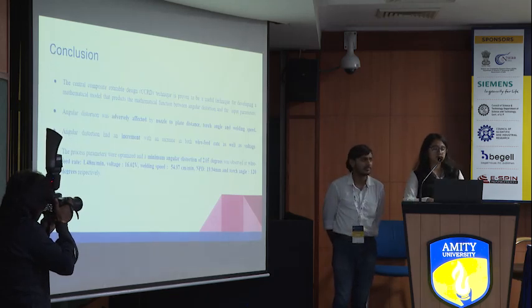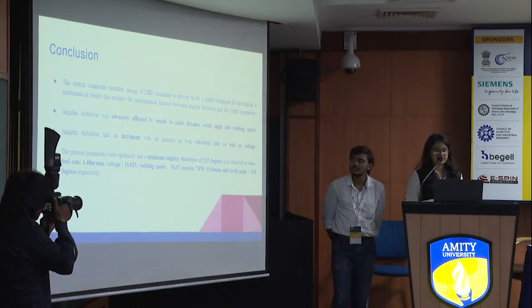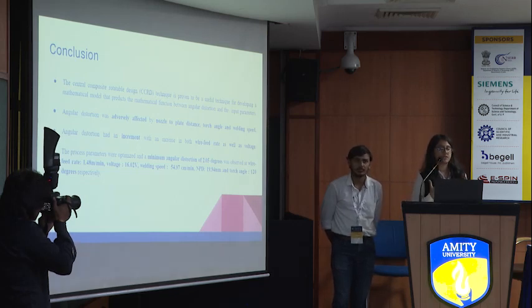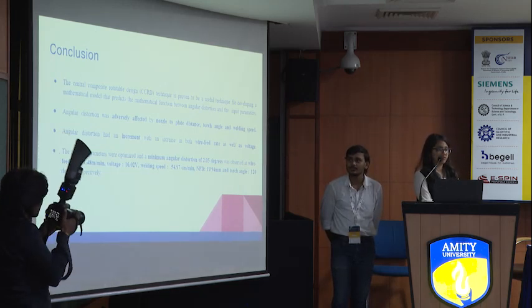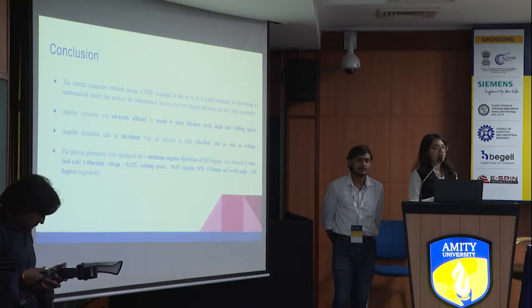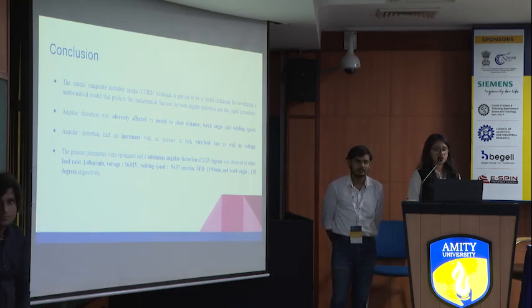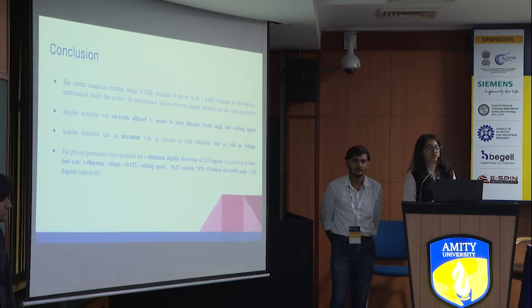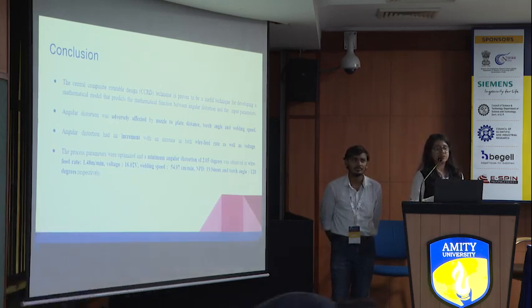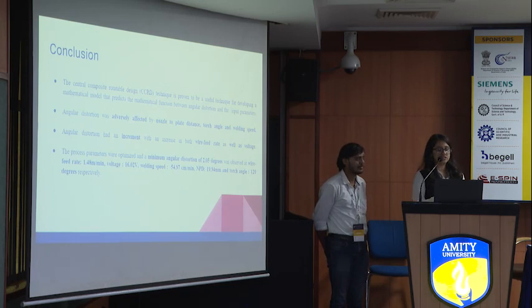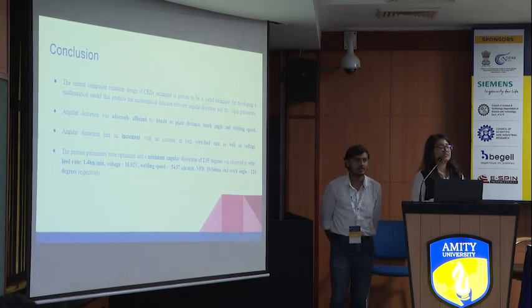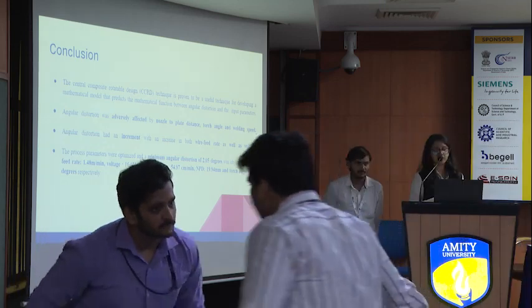The conclusion was pretty simple: the CCRD technique, central composite rotatable design, proved to be very helpful while we were developing the mathematical model to predict the angular distortions for our given input variables. Input variables were welding speed, voltage, nozzle to plate distance, torch angle, and wire feed rate. When we increase torch angle, welding speed, and nozzle to plate distance, the angular distortion has an inverse relation. On the other hand, there was an increment in angular distortion with the increase in wire feed rate and voltage. The optimized results are shown here.